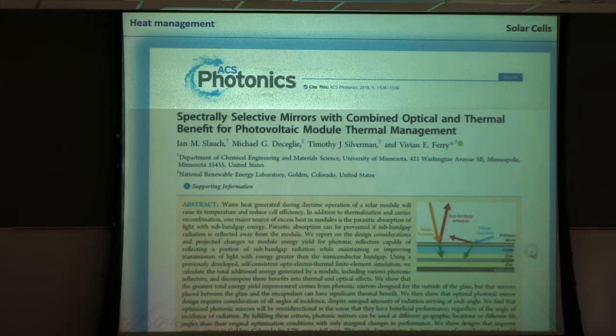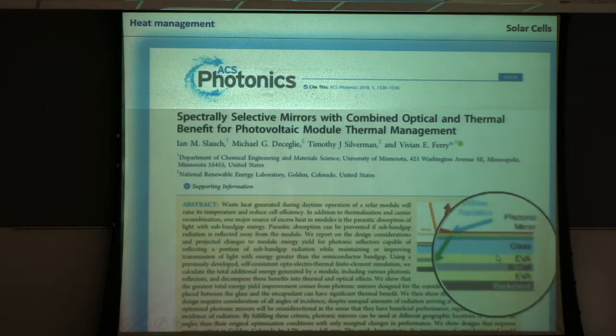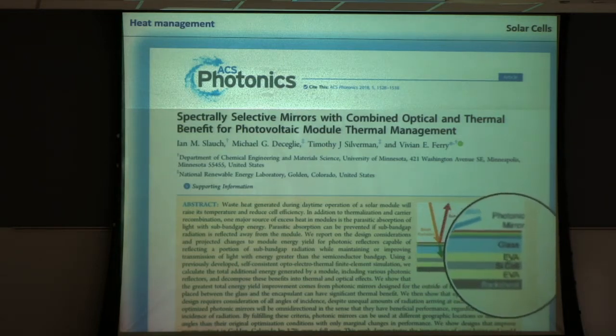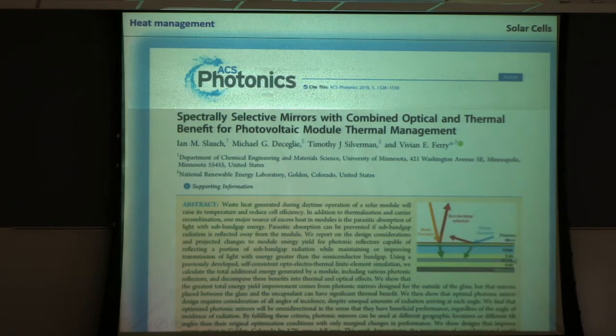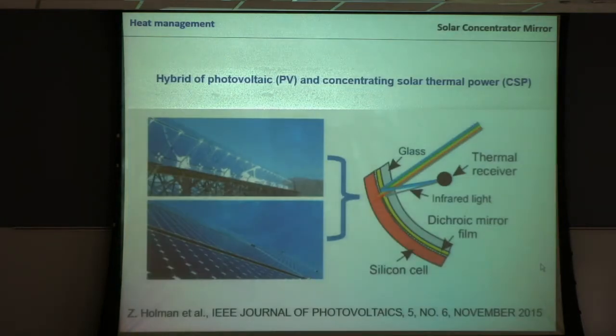And it looks promising because when you look at the inorganic, so that's a silicon cell, they actually have layers, here the EVA, that actually helps with light management. It gives a refractive index matching with the glass, so less light is reflected when it comes in from the glass into the silicon. So here now we can add the heat mirror, preventing the cell from heating up, and therefore it will not be affected by the heat. Clearly we can also use the reflected infrared.